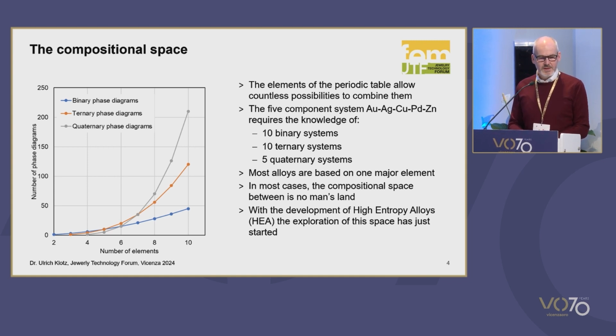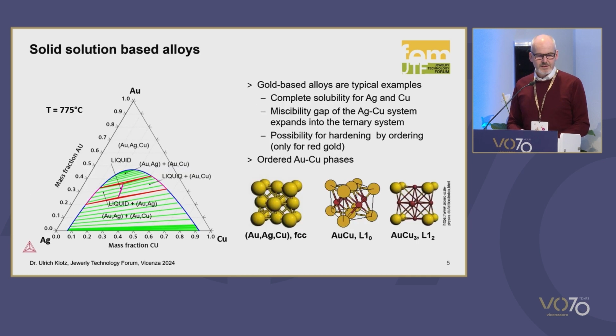needs to be explored. And there is a very interesting development going on at the moment, so-called high entropy alloys. This is a special class of alloys where all elements are mixed in a similar range. So 5 elements and every element around 20%. And it was found for steels or other aluminum containing alloys that such alloys are giving very interesting properties that are different from conventional alloys. So knowing all these systems experimentally is an extremely hard work and very difficult to solve. And therefore, we need some screening approaches, which I will talk about.